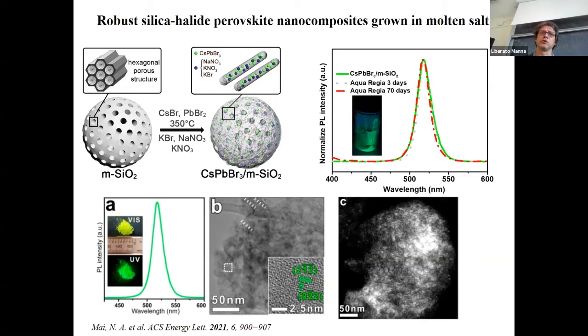So what we did recently was to grow perovskite nanocrystals inside the pores of mesoporous silica, and used a molten salt mixture as a solvent. This is not entirely new, but previous to us, this was done only at very high temperature, around 700 degrees. We managed to do this growth at 350 degrees. And we got mesoporous silica embedding nanocrystals at their interior. And the reaction conditions are also such that the external walls of this mesoporous silica are collapsed. So the nanocrystals are entirely encased in this mesoporous silica.